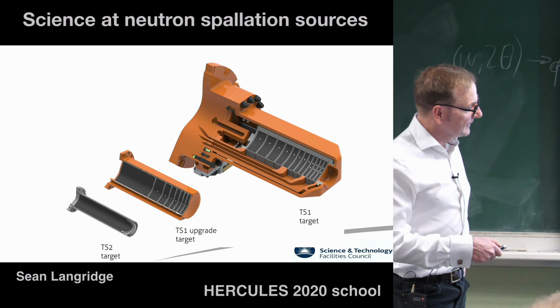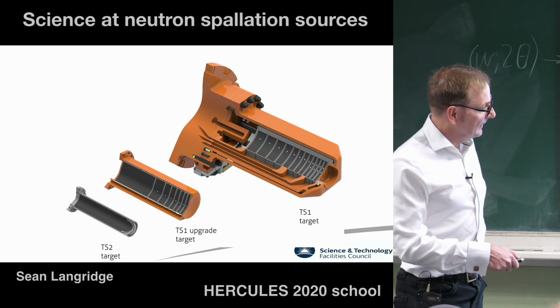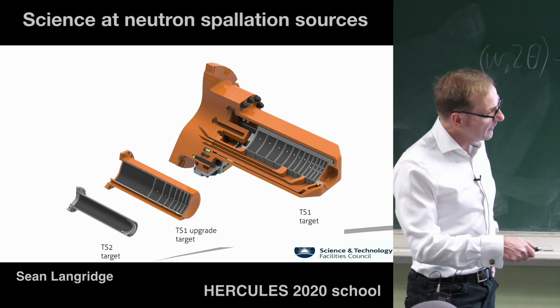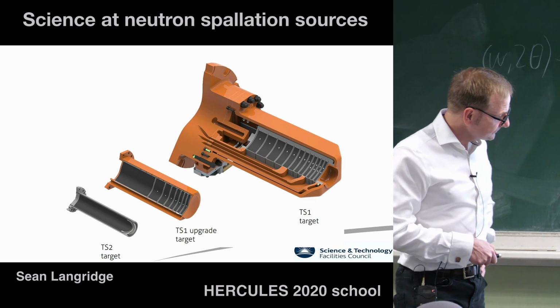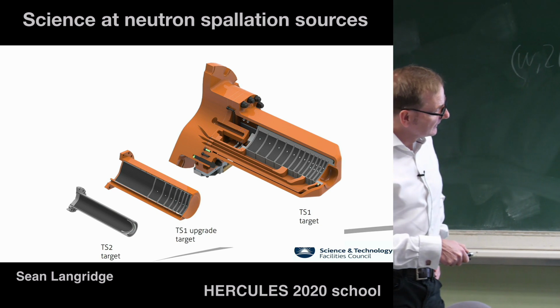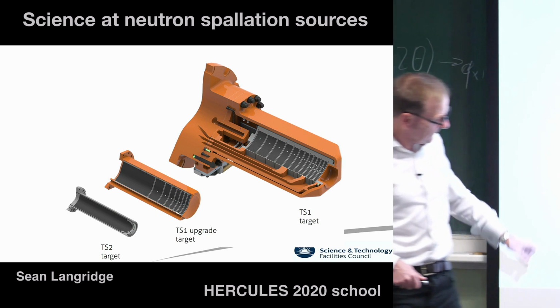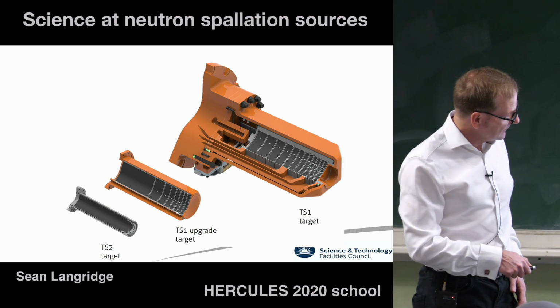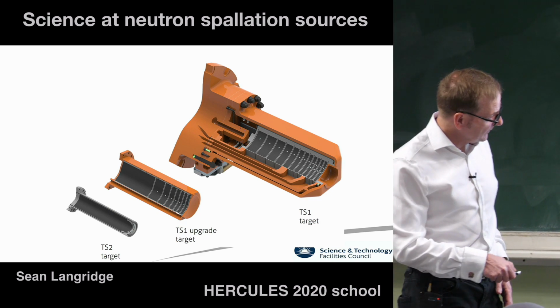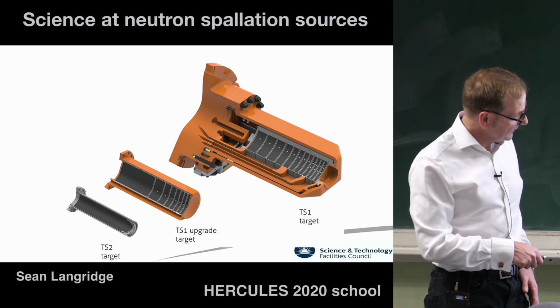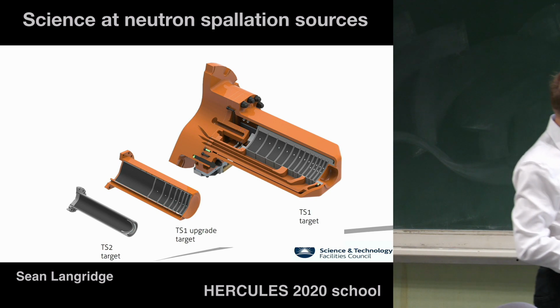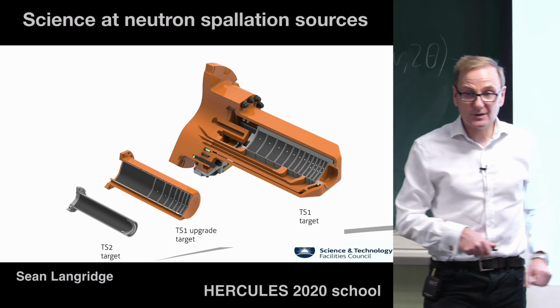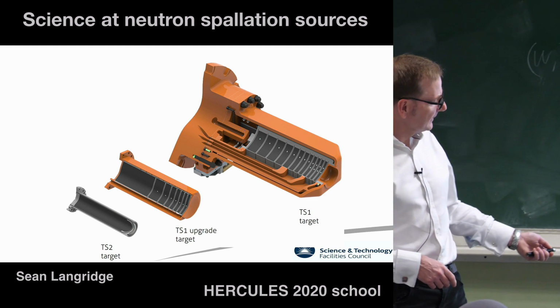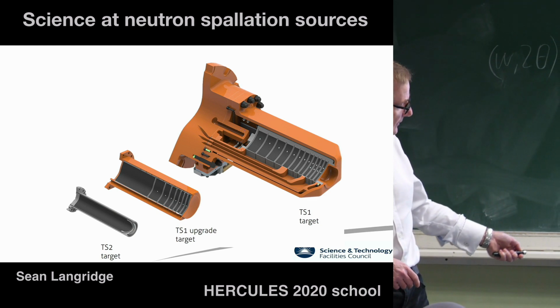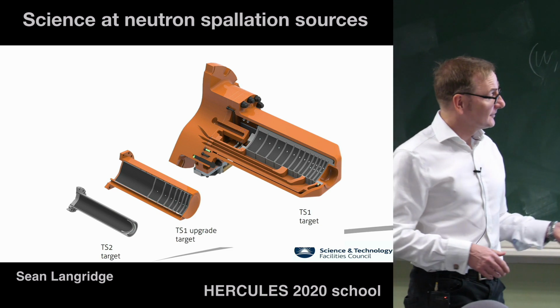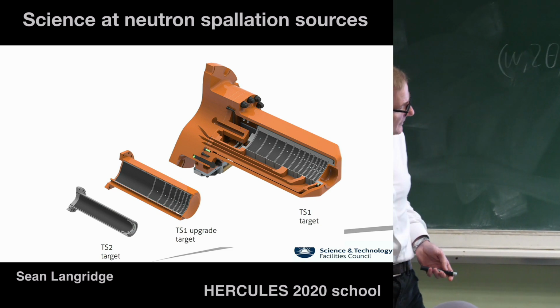Actually, we're in the middle of a new project which will start next year. 4th of January, we'll start a new TS1 project where we'll replace this target with a much smaller one. But this is what we have on TS2. So the TS2 target, again, is probably a factor 2 smaller than that. But you can see it's large. It's a single block of tungsten. Proton beam comes in here. Tantalum clad, and then we have some cooling on the side and on the face. So whilst this is 160 kilowatts, this is only 40 kilowatts. But actually, for certain classes of instruments, one can get more neutrons out of a 40 kilowatt target than you can out of 160 kilowatt. And we'll come on to that in a little while.